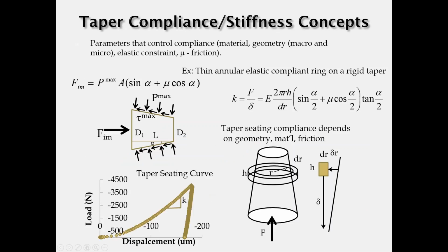So one concept that comes out of understanding these seating mechanics is the concept of taper compliance or stiffness. And that is that when you drive a head onto a neck, there's microtopography, there's modulus, there's a number of factors that influence how stiff that system is. And in this example, I'm showing a stiffness parameter K for a thin annular ring that's being pushed down onto a rigid trunnion. And so the equation for that engagement or that stiffness has the modulus of the ring, features of the geometry of that ring, the taper angle, the coefficient of friction.